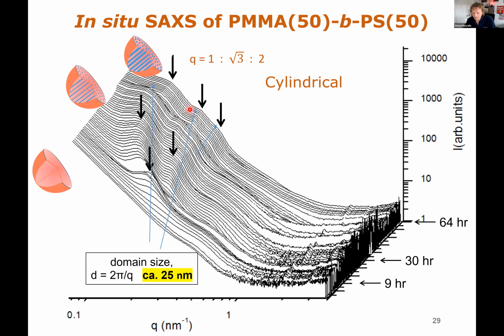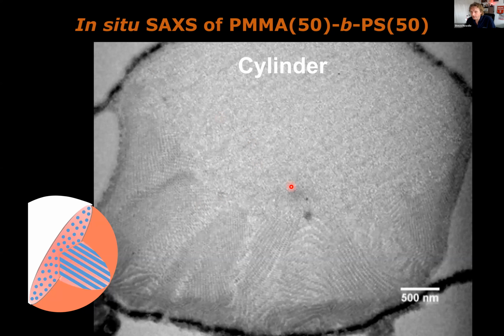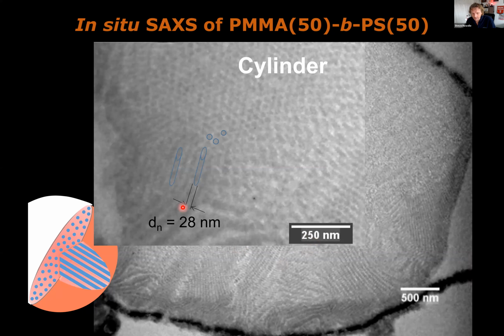So when we took these materials and put them in the electron microscope, here's one of those particles that's been cut in half. And what you can see is some structure inside here. If we analyze it, you can see that we have cylinders that have structure.